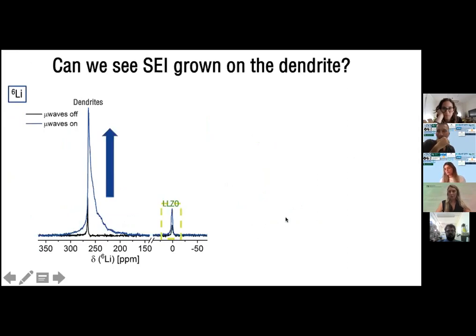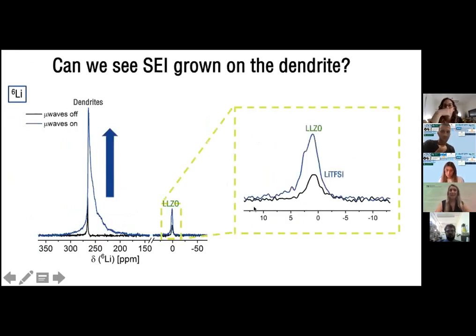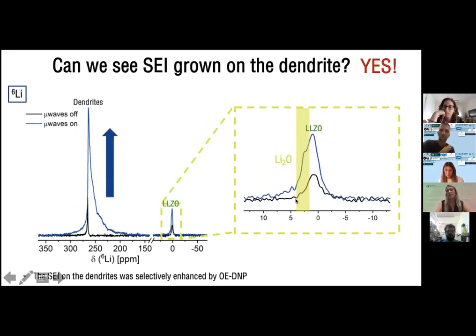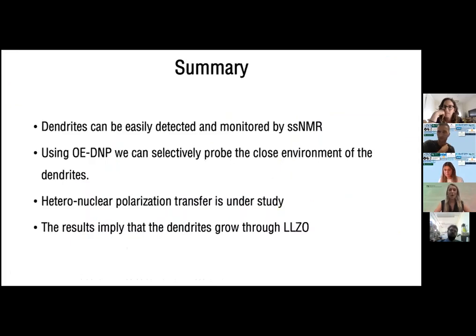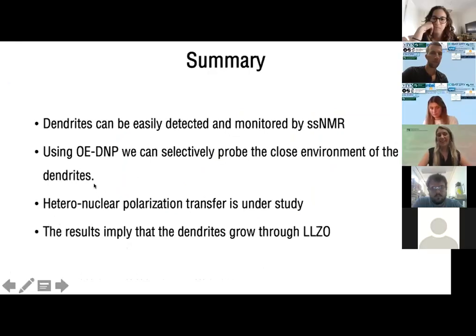And if we have such a good resolution, can we see what's happening on the SEI grown on the dendrites? So yes, we do. We see that the Li2O that is grown on the dendrites is enhanced selectively, and it's very amazing for me at least. So to summarize, I hope that I convinced you that using solid state NMR, we can monitor and detect dendrite formation and degradation. We can use Overhauser DNP to selectively probe only the environment close to the dendrites itself. Heteronuclear polarization between different nuclei is under study, yes, but probably it can be done. And theory also supports that. And the results imply that the dendrites grow through the LLZO.